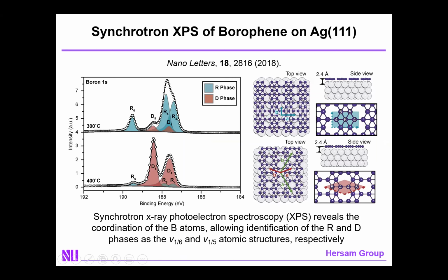In contrast, for the D phase, you see two distinct peaks. This suggests only two coordination numbers, and among the plausible 2D boron layers that have a diamond-shaped unit cell and only two coordination numbers, you find that the V1/5 structure is the one that meets those conditions. And that's where we have 1/5 of boron atoms missing in the triangular lattice.